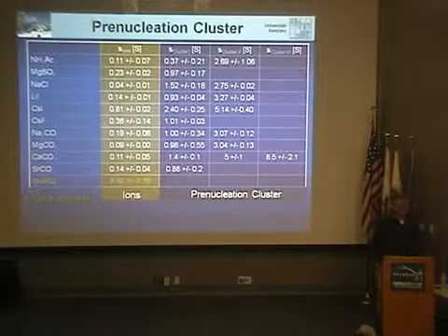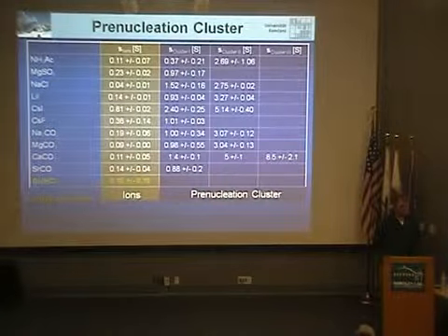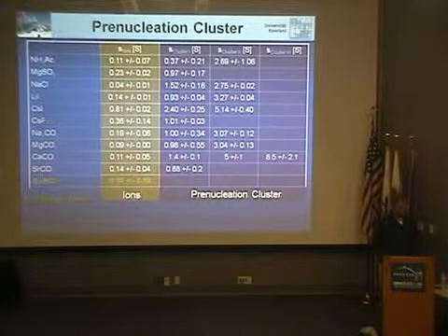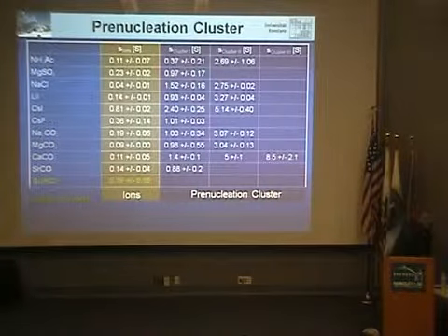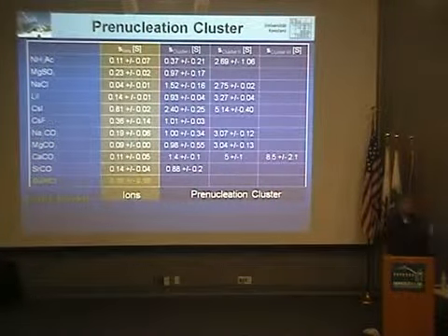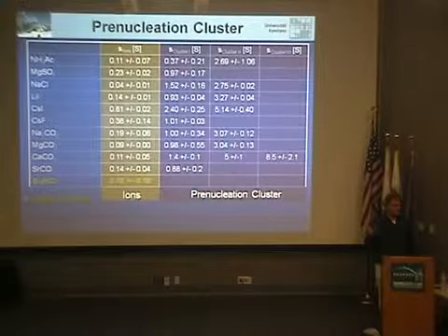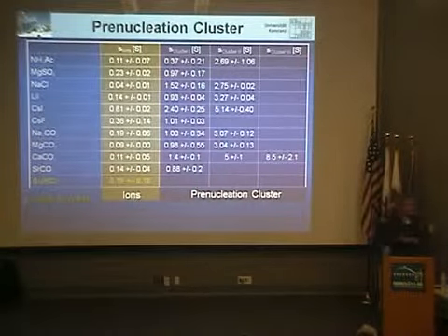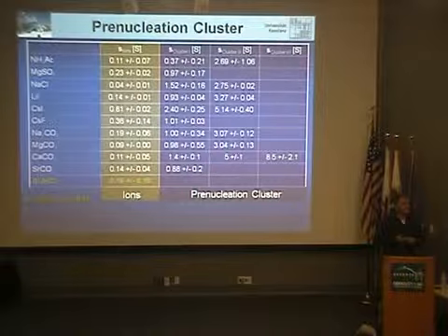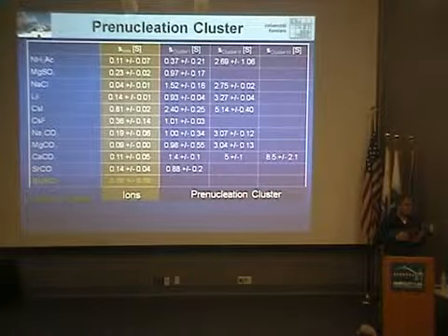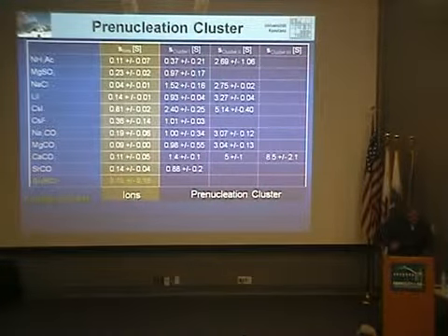One last brief question. Can you give me a quick idea of the concentrations at which you start seeing prenucleation clusters, and how do they compare to saturation? Yeah, that's a good question, because so far we detected them mainly by analytical ultracentrifugation, which works with refractive index detection. The calcium carbonate, we work with 10 millimolar solutions, so it's about that range. Yes, and you see, for example, it is an issue to detect them.